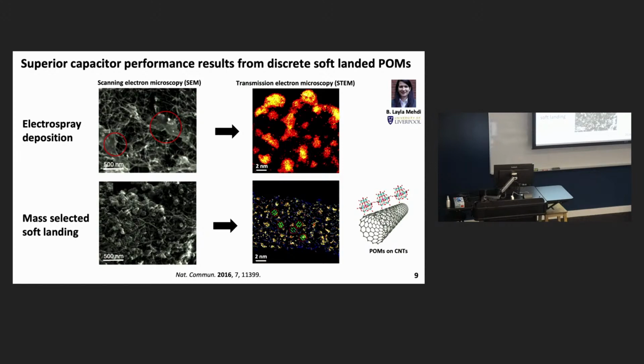At even higher resolution, now at about 2 nanometers, you can see in the STEM imaging that electrospray gives you much larger aggregates, whereas mass-selected soft landing in vacuum gives you discrete clusters in intimate contact with the surface. And in fact, if you rotate this known structure of these clusters, you can actually line it up and identify species as being intact polyoxometalates. So we think, in a cartoon sense, we've produced something that sort of looks like that on the right-hand side.